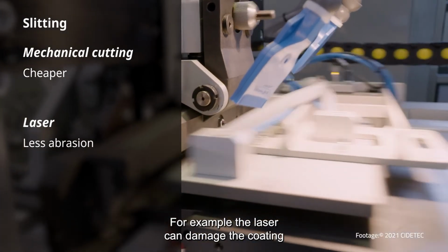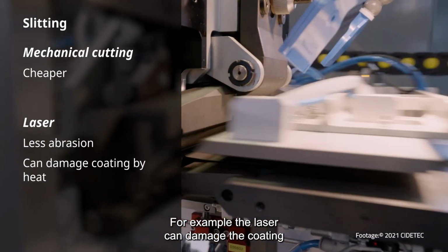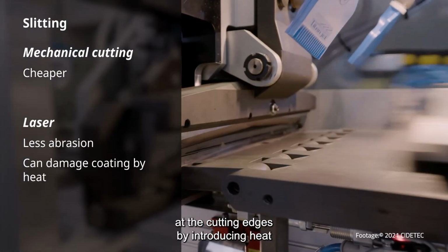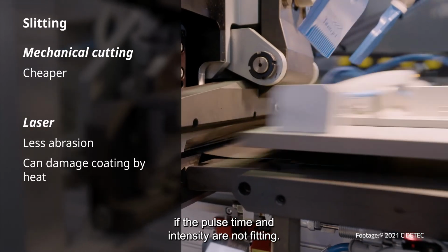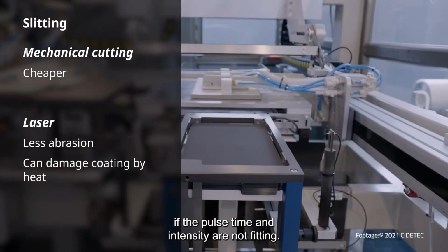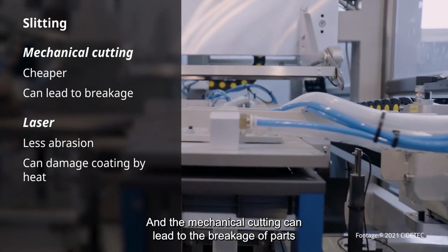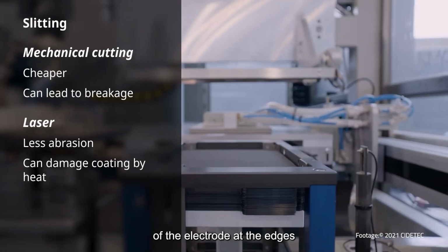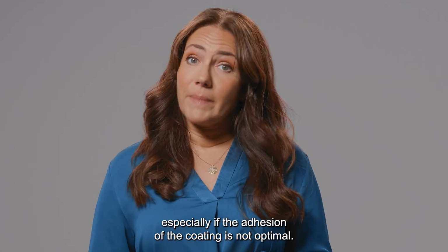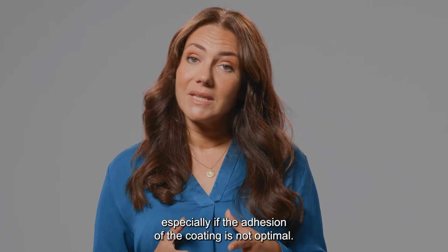For example, the laser can damage the coating at the cutting edges by introducing heat if the pulse time and intensity are not fitting. And the mechanical cutting can lead to the breakage of parts of the electrode at the edges, especially if the adhesion of the coating is not optimal.